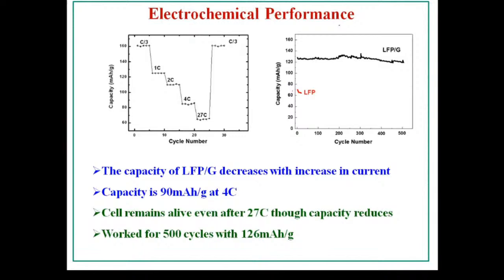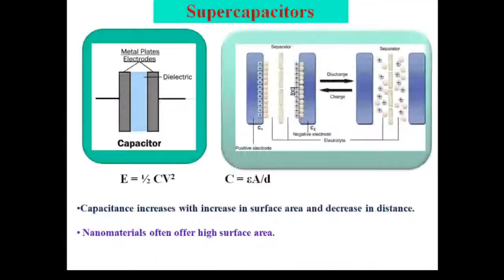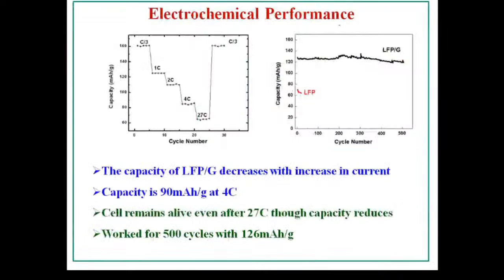And here the capacity, I'll show you at C/3 rate. C/3 rate means we are slowly charging, gently charging the mobile, and there we got 160 milliampere hour per gram. Basically, the theoretical maximum value we can attain is 170. So we could really reach 160 or so, around 94% of its theoretical value. And that I have written here, that 500 cycles we got.